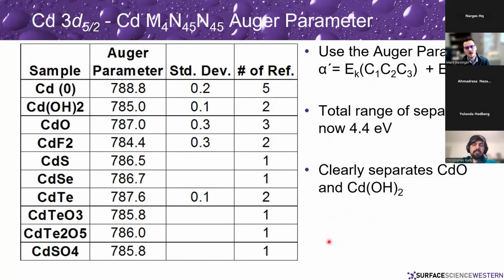Whereas if we look at the Auger parameter, we now have a range of separation of almost 4.4 eV. So we've got a much bigger range of separation. So that allows us to clearly separate out different species a lot more easily. And so that's just another tool that we have that allows us to pull out what species that we have.